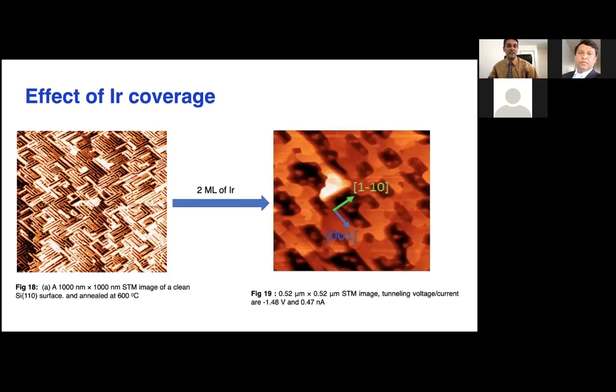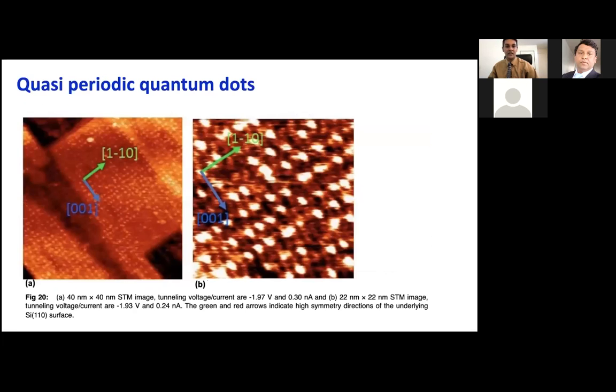Okay, so we followed the same procedure all the way up to getting the clean silicon 110 structure. Then after that, we deposited 2 monolayers of iridium and took scanning STM images. Instead of seeing the longer nanowires, we saw flat terraces covering the surface. But these flat terraces are not atomically flat. When we look closely at the terraces, we saw they are covered with quasi-periodic quantum dots.